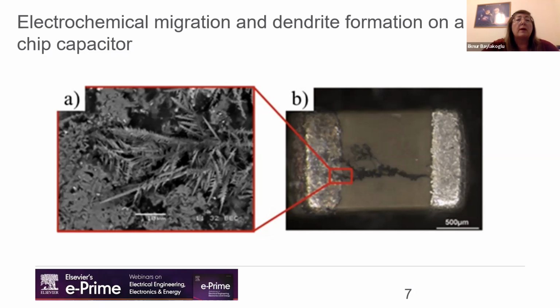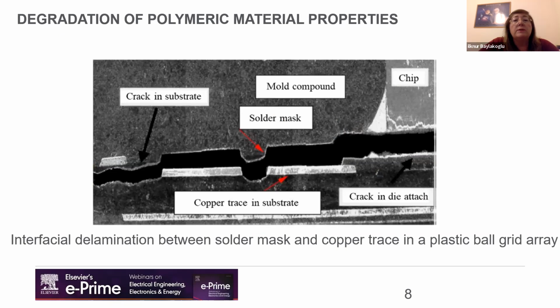And the effect of moisture and water on the material properties is also very important, especially for some polymeric materials. It causes the degradation of polymeric materials. Of course, we have lots of different materials in an electronic device. We have some polymeric materials, some metal structures, some ceramic materials. These polymeric materials absorb moisture and change their physical properties. It can change the volume, it can change the elastic modulus. Since the water molecules are interposed between the molecules, they may disturb the original interactions. This type of degradation can be observed in polymers, especially because they are hydrophilic materials. Hydrophilic materials are attracted to water molecules.